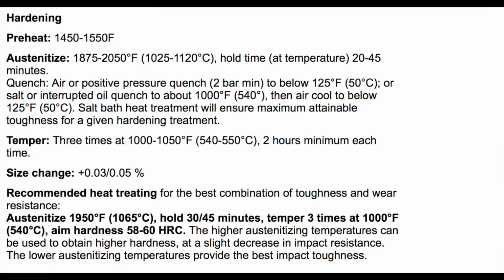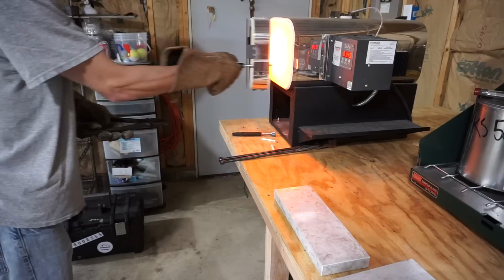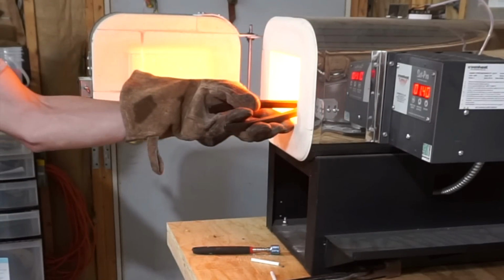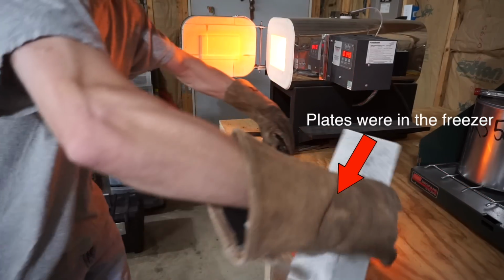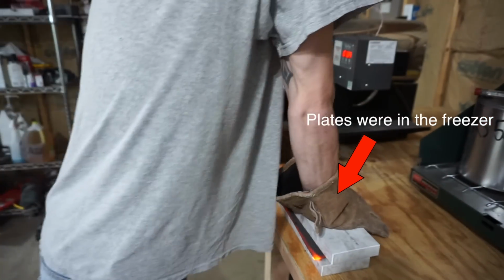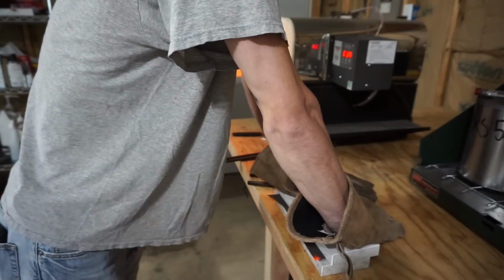So for the actual heat treating recipe, we austenitized this at 2050 degrees for 20 minutes and then plate quenched this between two 0-degree Fahrenheit plates. The plates were just in the freezer at 0 degrees, nothing special. And that just helps pull as much heat out as possible as quickly as possible.